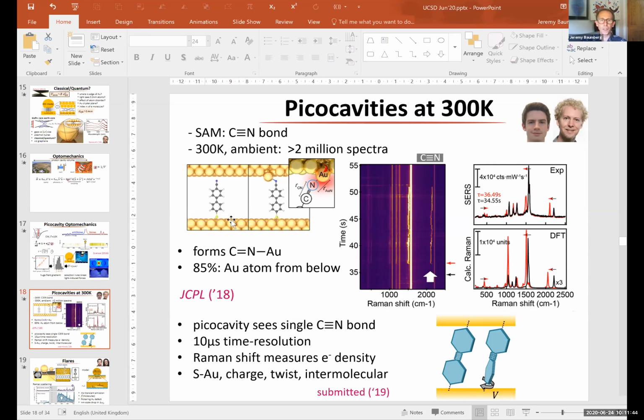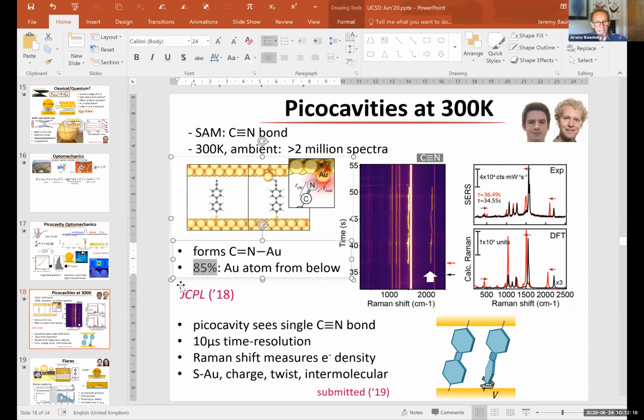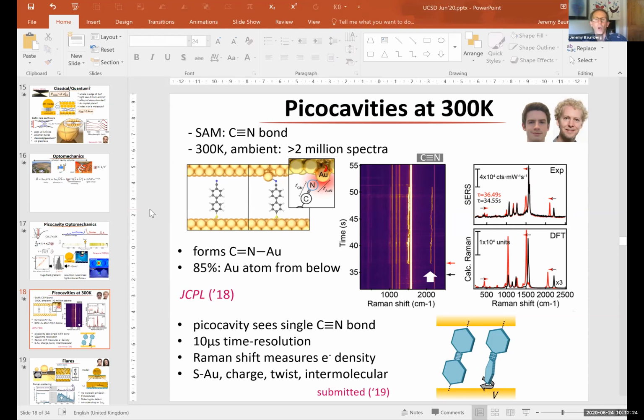The problem, if you're using gold, is that the SAM is very robust, the Young's modulus of the SAM is actually higher than that of the metal. So essentially it pushes the gold atom back into the metal when you make this structure. The other thing that people will often say is it looks symmetrical, but of course you prepare it by making the SAM on the flat gold first, and then you bring the nanoparticle on top. And it turns out that it is indeed asymmetrical, and we can really clearly see that. So we've done a few systems where we can see that that asymmetry gives you more of a chance of pulling the gold atom from the bottom than from the top, and we're trying to understand what controls this. So it's an interesting way of trying to visualize what really goes on in the gap here.